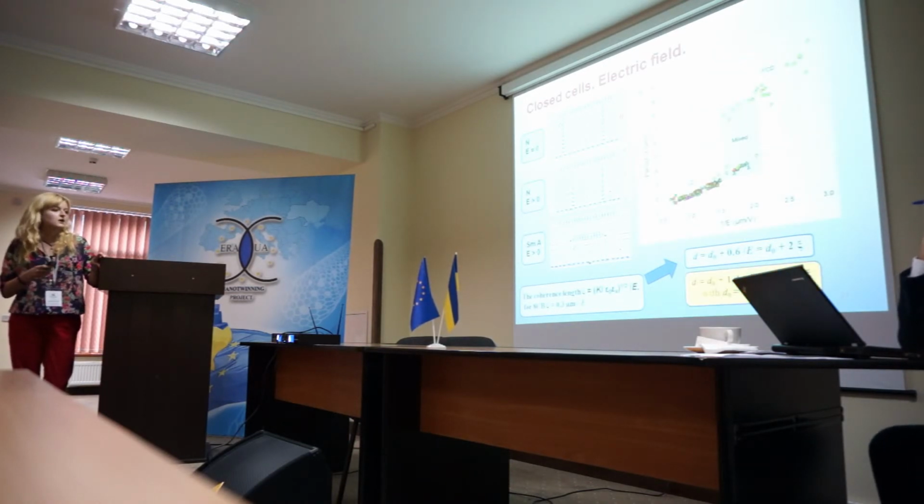And this region where we create our linear defect domains would in this case be determined by the electric coherence length. When we compare our results obtained for the zero field and for the applied electric field, we again have a linear dependence with the same intercept of 0.3 micrometers, which suggests that probably this model is correct.